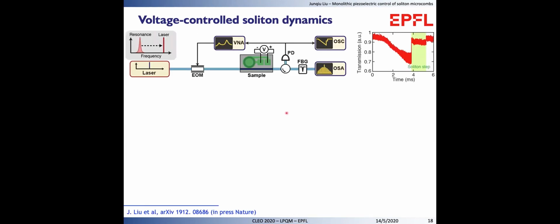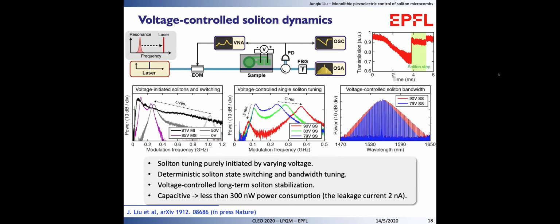With this new capability, we show here voltage-controlled soliton initiation and switching. Here, we use a laser with a fixed frequency and apply the voltage on the aluminum nitride actuators to tune the resonance to the laser. When the resonance scans across the laser, a soliton step is observed. By applying different voltages, we can initiate the soliton and control the soliton detuning values, which in turn change the soliton bandwidth. This also allows us to stabilize the soliton detuning over the long term via active feedback. Note that the power consumption here is only 300 nanowatts, caused by 2 nanoamp leakage current.